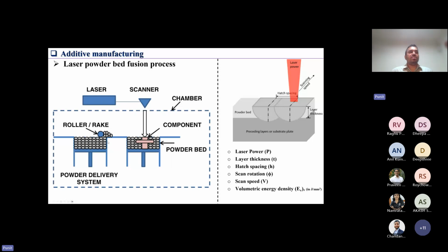Usually in this process you have a powder delivery system where you spread the powder on the powder bed, and you use a scanner to selectively melt the material, and you get a final 3D component by lowering the powder bed layer by layer.